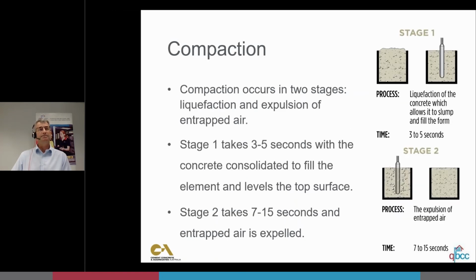Okay, so this is the compaction process. You put the vibrating probe in, and there's stage one, a few seconds just to liquefy the concrete, and then stage two, you'll see the bubbles coming out, and most of that entrapped air should be gone within 7 to 15 seconds. But you'll see that the pokers are inserted vertically. They're not used in a horizontal fashion.